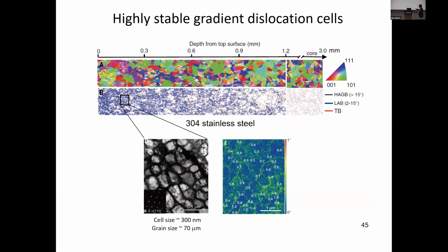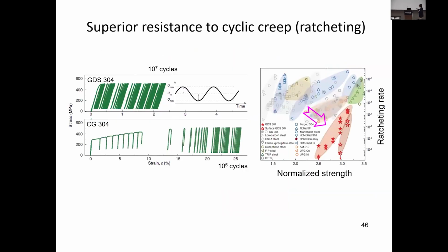So let's first look at this microstructure. Again, it's 304 stainless steel, right? So it's a very robust and reliable material. For example, SpaceX uses it for their rocket to Mars. So as you can see, we have the dislocation cells with the size about 300 nanometer in this case, with a gradient distribution of their size.